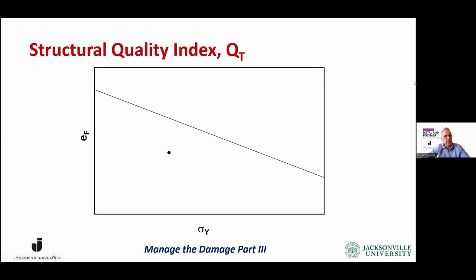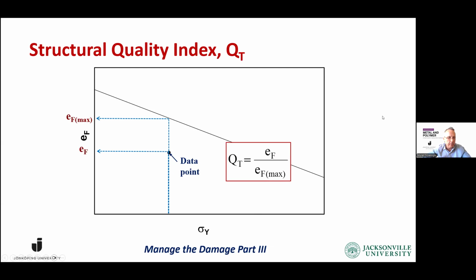And this brings us to the structural quality index. Now that we have a metric to compare to, we can have a quality index, QT, where this is our data point that comes from our tensile test. It obviously has a yield strength and an elongation. I can then calculate a value from the previous equation, and similar equations exist for aluminum copper alloys if you are interested. Then I can define the quality index as the elongation that I obtained divided by the ductility potential. So what is the measure of damage then? Damage is the part that I'm not getting from my casting, and that's the loss due to damage.